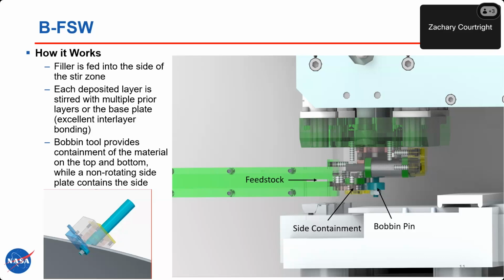So going from that image on the right to the image on the left, you can see a greatly reduced amount of intricacy for the tool. But basically the way that this works is the feedstock travels in from the left side of this picture on the right, through this green part here, into a containment block, and then through that containment block into the stir zone between a standard bobbin or self-reacting friction stir tool. So it feeds right into that stir zone.